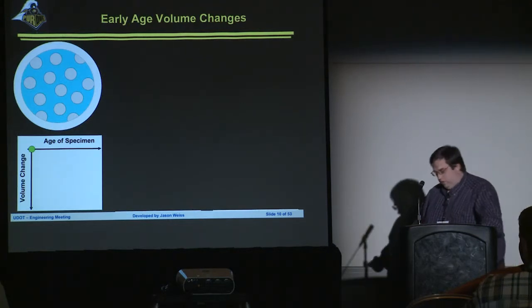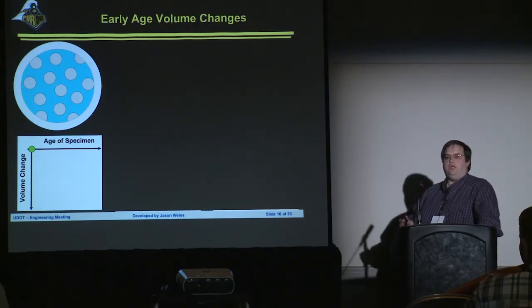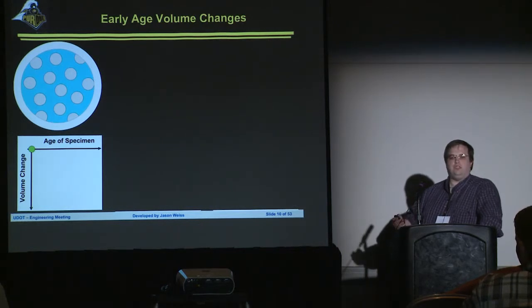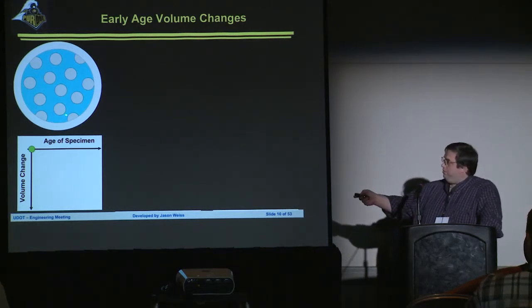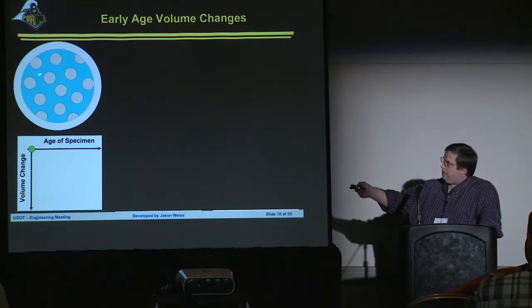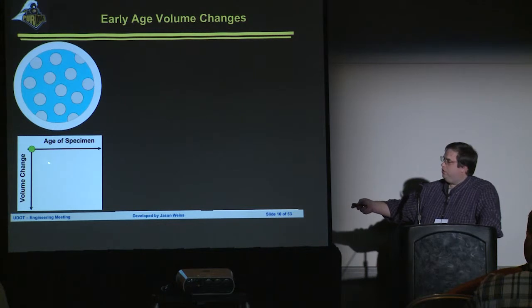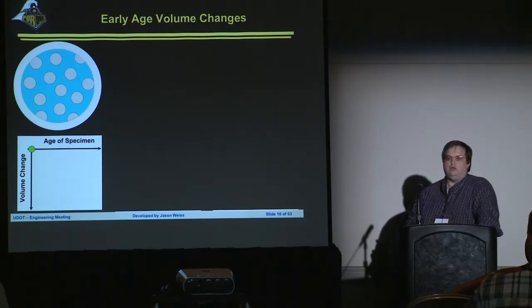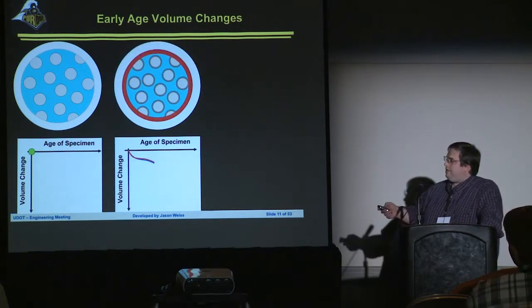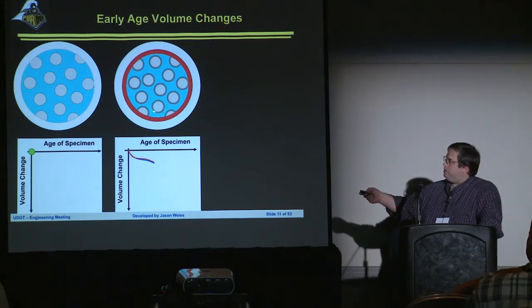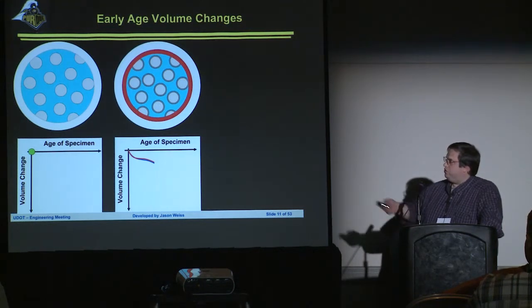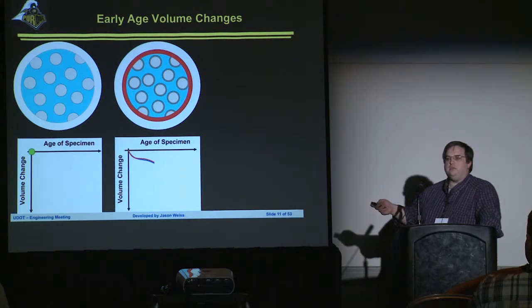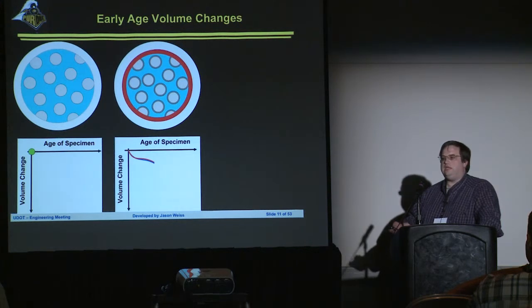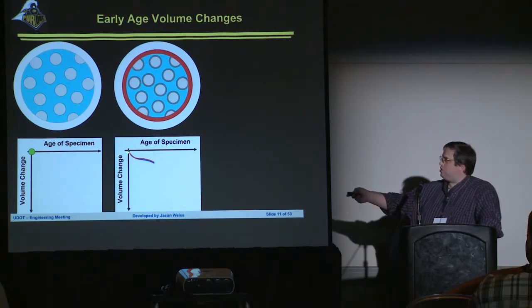Right, now what I want to do is take a second and think about what's happening and what's giving rise to this concept of self-desiccation in the system. So, being an entirely poor artist, what I've drawn are spherical cement grains inside of this pore solution. And what we're going to do is monitor the volume change that occurs over time. As the cement particles start to react, you can see these rims reacting, or you can see some through-solution products reacting. The system, as we just talked about, gets smaller. As the system reacts, chemical shrinkage occurs and the system gets smaller.